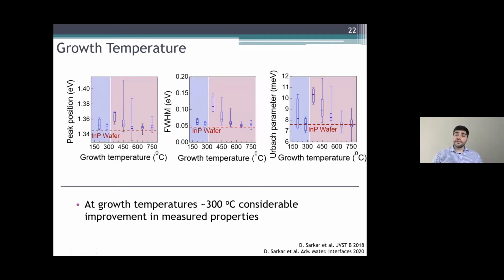However, what we found is that if you continue down and drop to about 300 degrees C or so, what ends up happening is that somehow, I'll say magically, even though it's not magic, the properties of the material start to get better again. And by better, I mean the indium phosphide grown at about 300 degrees C on a non-epitaxial template starts to more strongly resemble our single crystalline wafer.